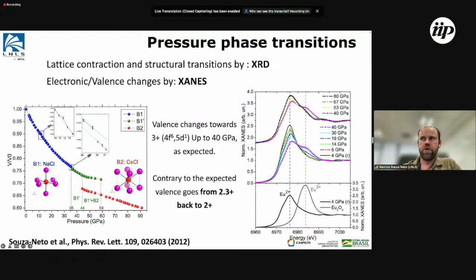like in here, where we look at the valence, which is a measure of the electronic oxidation state of the material, with the same pressure. And actually, if we look only at the structure information and try to guess the electronic configuration of the material, depending on the theory, we get it wrong. From time to time it is good to directly measure the electronic information. In this case, we more or less prove that the bond valence theory gets something wrong from time to time.